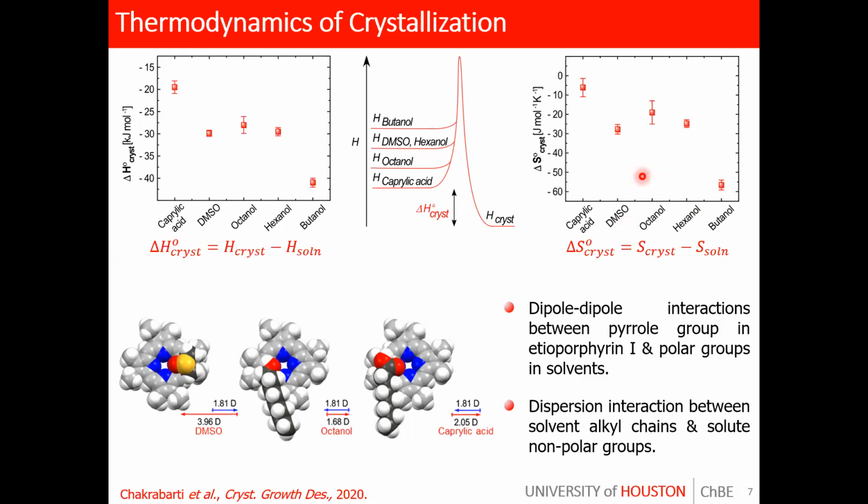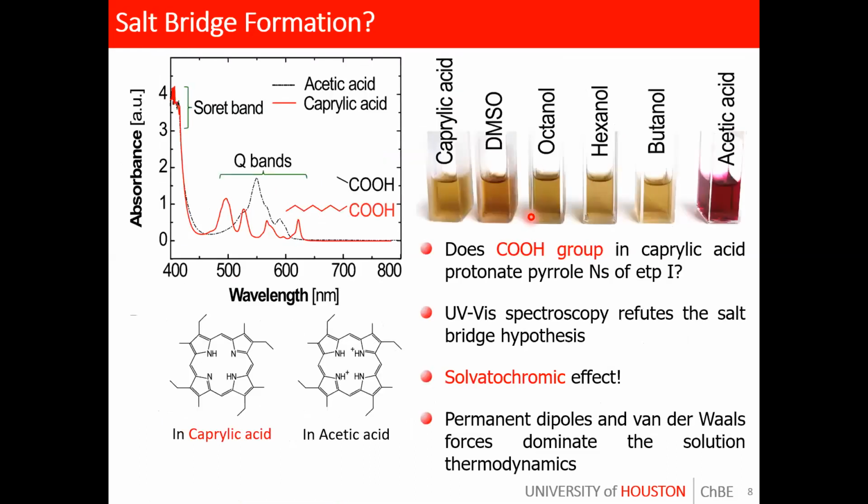And this conformity of trends for enthalpy and entropy of crystallization suggests that the solvent structuring at the crystal interface is weak and it's only supported by solute-solvent interactions. Organic liquids, unlike aqueous solutions, have very weak solvent-solvent bonding, and as a result, a strong structuring of solvent doesn't occur at the crystal interface.